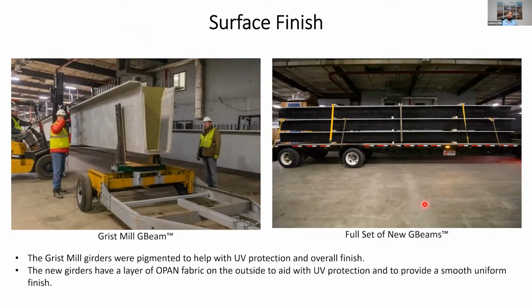Another thing is the surface finish. When we did Grist Mill, Maine DOT wanted to go with a gray color at the time, but more importantly, we wanted to use a pigment to help with UV protection, and so that was the product. It was good. The standard was blemishes from a distance of 20 feet visually. However, since then we have been using an OPAN fabric, also from Tech Industries. It's an opaque layer, so it does help with the UV protection, and it's the sacrificial layer on the outside. It's non-structural, but it also provides a very smooth, uniform finish with the least amount of time in post-processing.